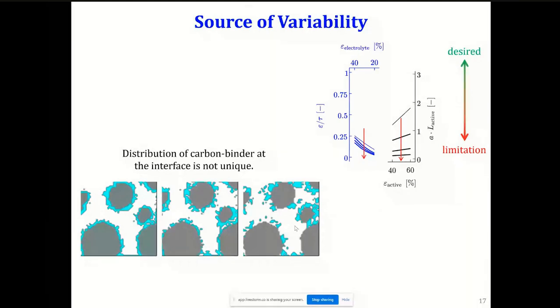You have another question. A lot of questions says, how does intercalation kinetics influence these results? So intercalation kinetics would directly relate to the area that you have available for reaction. More or less the only thing you can change for reaction kinetics is area, right? You can do other things for transport, like change the length or change the morphology, but with reaction, more or less the only thing you can do is area. Then it's the property of the active material and the electrolyte that you use. So it's a property of the interface, and you really can't do much about it. It is what it is.